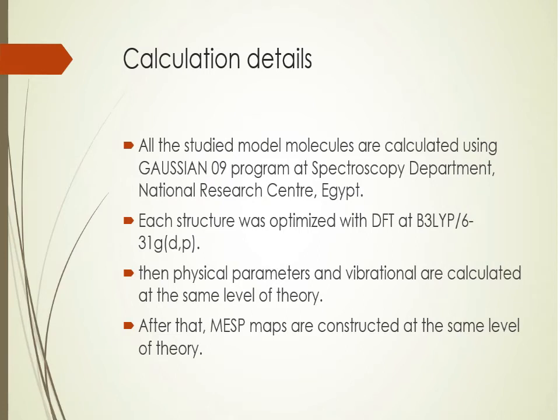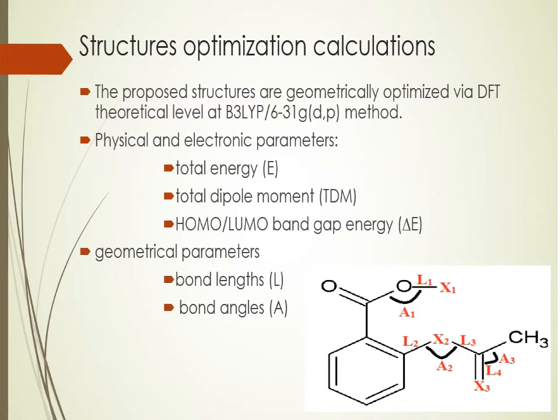Each structure was optimized with DFT at B3LYP. Physical parameters and vibrational modes are calculated at the same level of theory. After that, MESP maps are constructed at the same level of theory. The physical parameters that we calculated are total energy, which reflects the stability of the structure; total dipole moment, which reflects the reactivity; and HOMO-LUMO band gap energy, the energy needed to convert the structure to be a conductor. Also, we calculated geometrical parameters: four bond lengths, L1, L2, L3, L4, and bond angles A1, A2, A3.